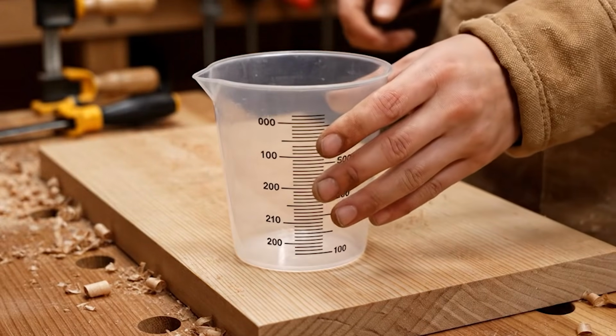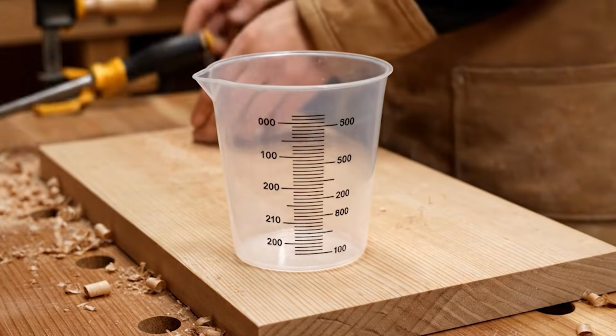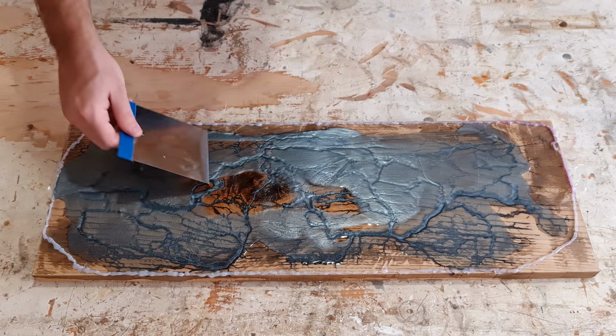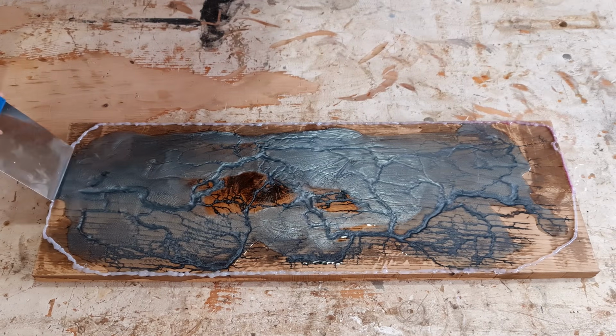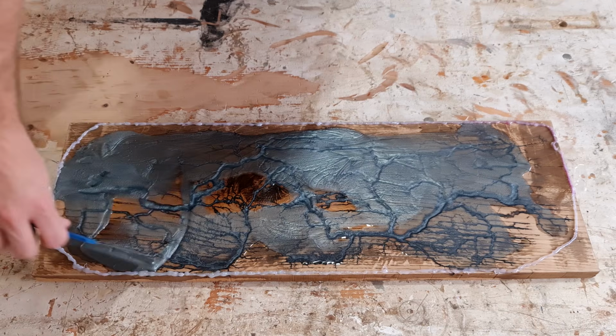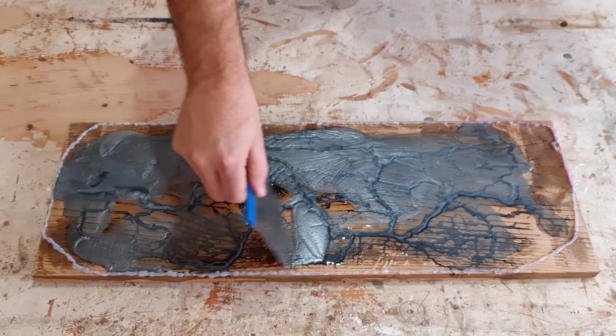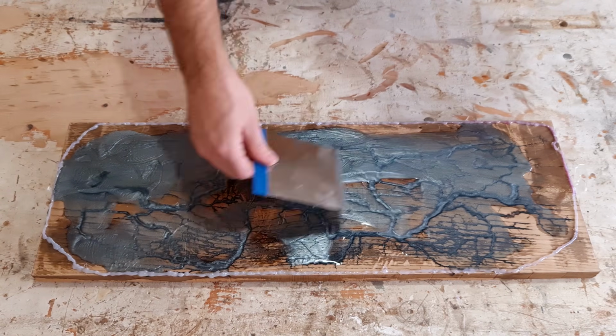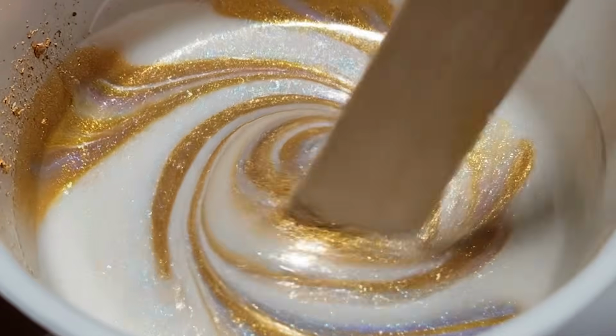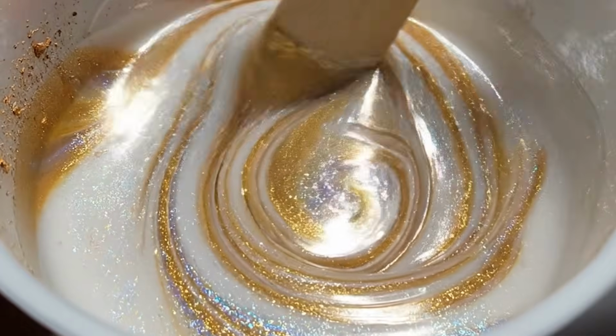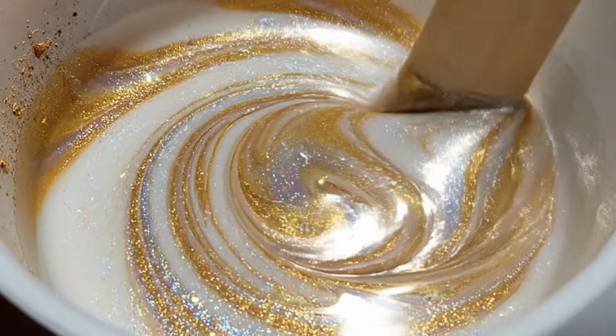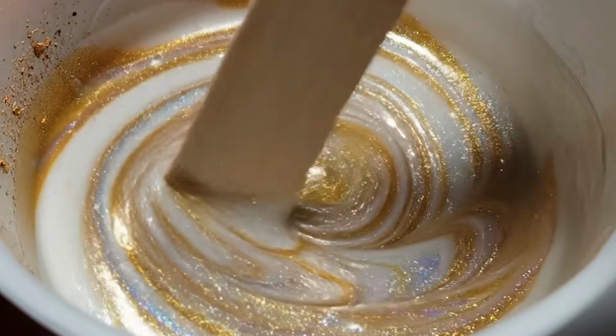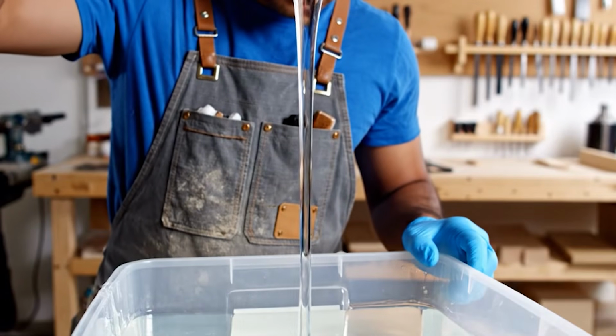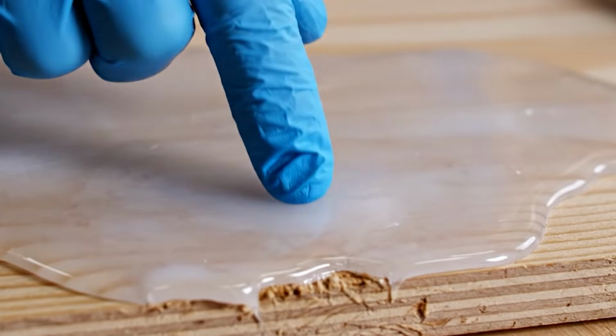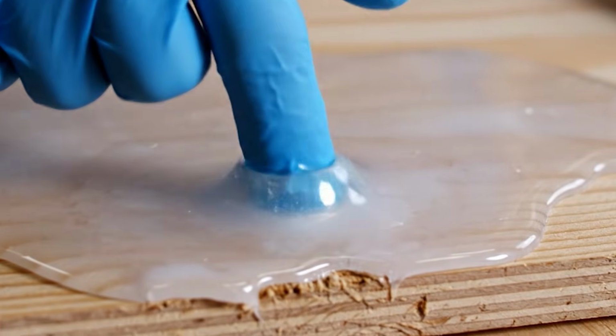Now mix your epoxy according to the manufacturer's instructions. This is not the time to eyeball it. Use graduated mixing cups and measure your resin and hardener precisely. Most deep pour epoxies use a 2-to-1 ratio by volume, but always check your specific brand. Stir slowly and thoroughly for at least 3 to 4 minutes. Scrape the sides and bottom of your mixing container as you go. Undermixed epoxy will leave you with soft, sticky spots that never fully cure, and that'll ruin the whole project.